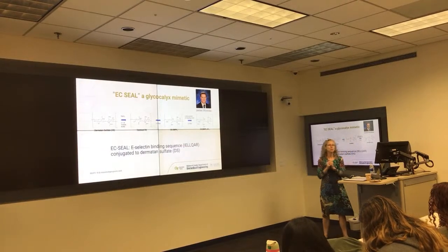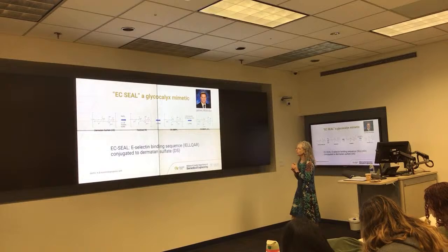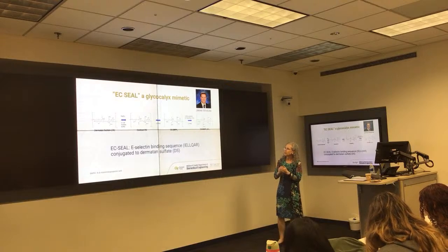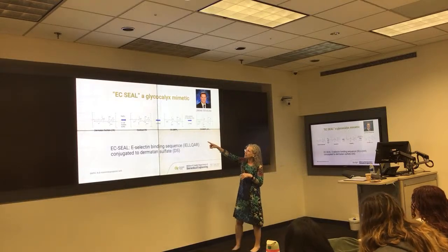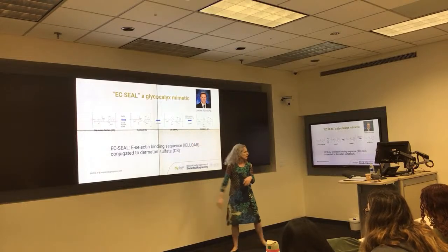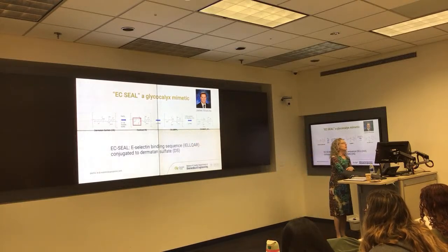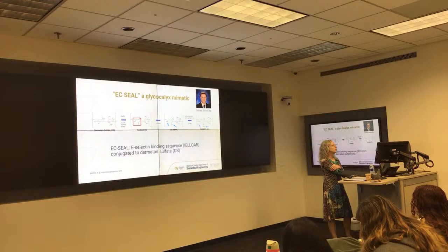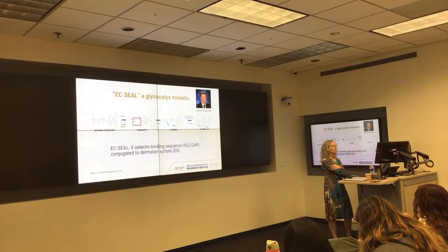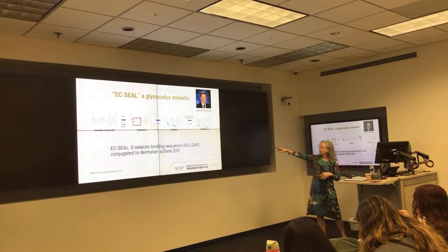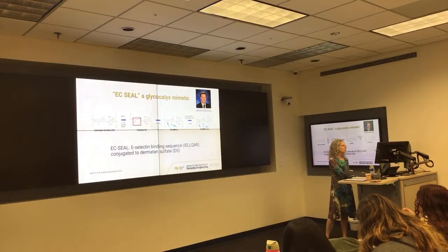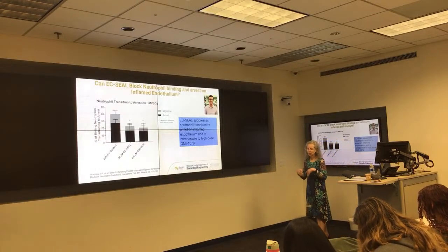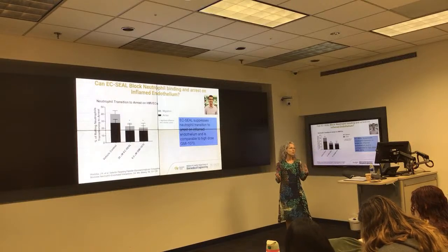All right, so James Wadika, who was an MD PhD student in my lab, he's now a cardiology fellow at Emory, designed the first molecule, and he took dermatan sulfate, he oxidized it, so you can see the ring structure opens up and there are aldehyde groups, and I bet this is animated. Yep. And then he could put a hetero-bifunctional cross-linker on the molecule called BMPH, and that allows us to add the peptide handle. The amino acid sequence is shown here, and again, conjugated to dermatan sulfate. And then he did a lot of work to show the peptide was conjugated, the molecule was what we thought it was, a lot of other in vitro work.